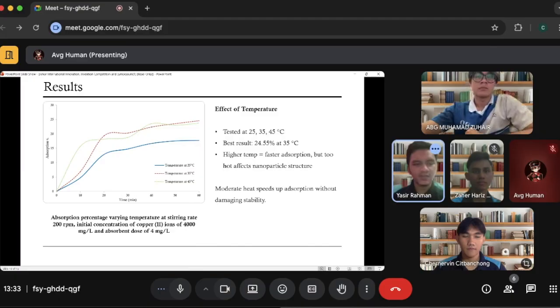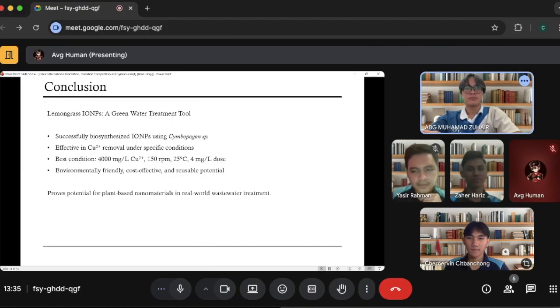The last variable is the effect of temperature on adsorption performance, which was tested from 25 to 45 degrees Celsius. From the results, the best adsorption occurred at 35 degrees Celsius. Higher temperature results in faster adsorption due to kinetic energy provided to the ions to travel, thus increasing diffusion and mass transfer. However, increasing the temperature to 45 degrees Celsius did not show any positive impact.